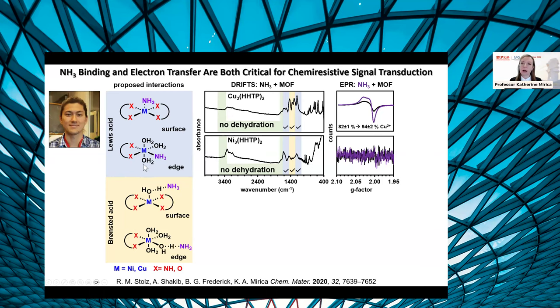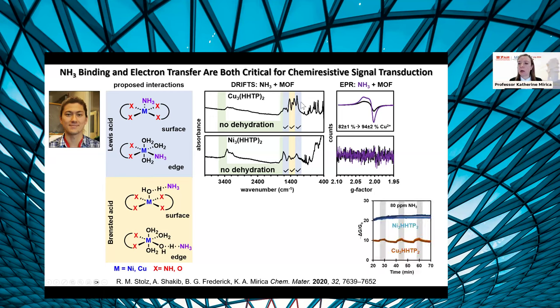So both Bronsted acid sites and Lewis acid sites are present, but there is an important distinction between the copper-based material and the nickel-based material, less so in the binding regime, but more so in the electron paramagnetic resonance, where for the nickel-based materials, we don't see any changes in redox activity of either the ligand or the metal. But in the case of the copper-based materials, we actually see a shift in redox states of the copper metal that starts out as being mixed valency, a mixture of copper 1 and copper 2, that shifts significantly towards more copper 2 population upon exposure to ammonia, which upon binding, we hypothesize, can stabilize this higher oxidation state of the metal and potentially lead to a metal to ligand charge transfer that ultimately leads to the observed chemiresistive response for the copper-based material and the lack of chemiresistive response for the nickel-based material.